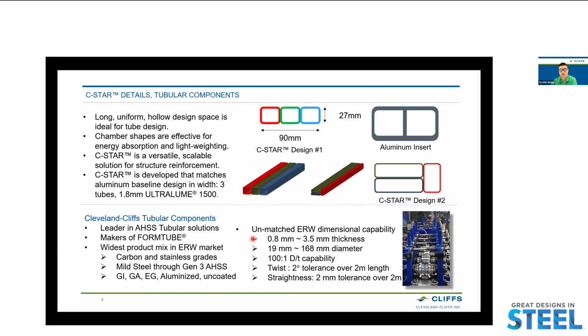We have the unmatched ERW dimensional capability. From thin gauge to thick gauge, small diameter to large diameter, 100 to 1 D to T ratio, this is really the capability that distinguishes us from other tube makers. We can also achieve a superior tolerance control. For the twist, we can maintain 2 degrees over 2 meter length. And for the straightness, we can have a 2 millimeter tolerance over 2 meter length.